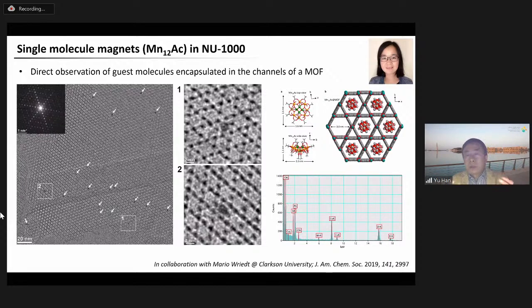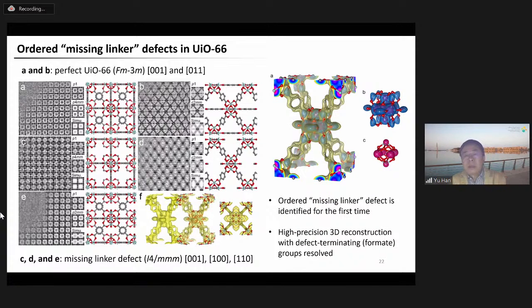And we also studied structure defects in MOFs. The existence of missing linker and missing cluster defects in MOFs has been speculated from indirect evidence, but it has not been directly observed prior to our study. So now with HRTEM, we can see where the defects are and whether they are ordered, and if they are ordered, what the domain size is and how the domains are distributed within the crystals. All this information can now be obtained. So in this particular case, we observed missing linker defects in UiO-66.